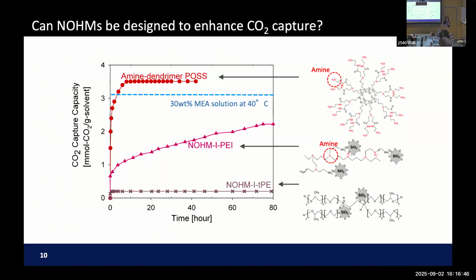Now we just need to put it into huge reactors. At this point, we were still making tiny microliters of this material, doing all the fun stuff. So then my student asked me, oh, so we need to put this in the reactor? And if you look at the little bottle we have of NOHMs, if you flip it, it doesn't free flow. It's really highly viscous material. If you look at second generation CO2 capture liquid solvents, water lean and waterless, they are high viscosity. Ionic liquid is high viscosity, NOHMs is high viscosity, many of these are high viscosity, and that's why almost no vapor pressure. So good and bad at the same time.